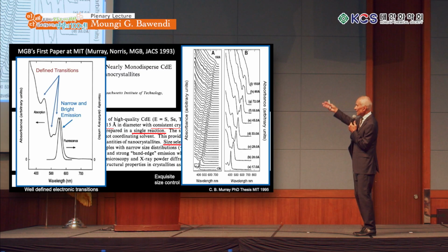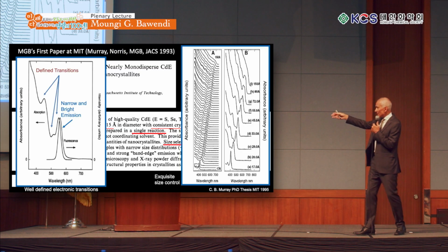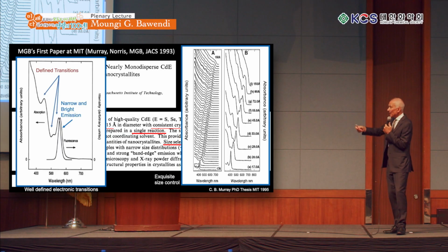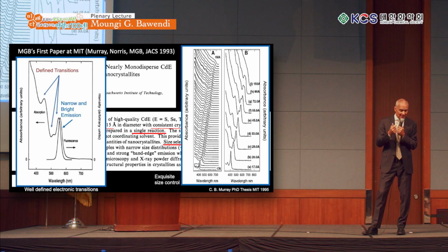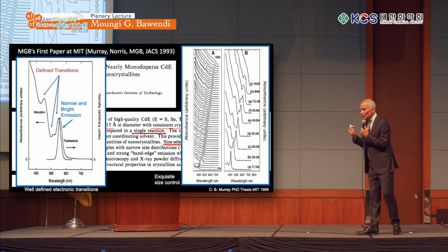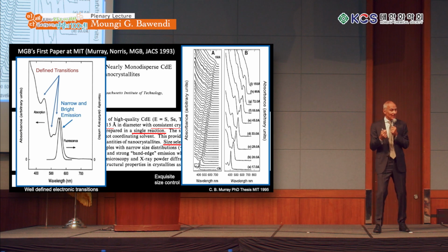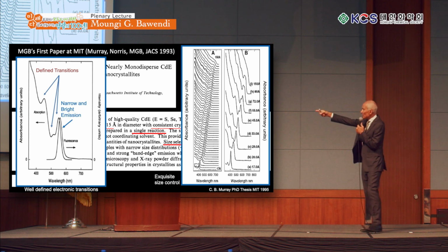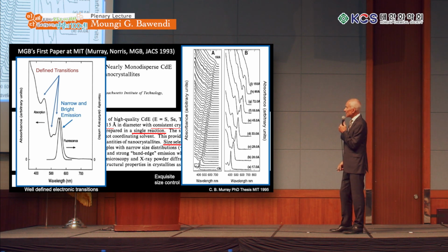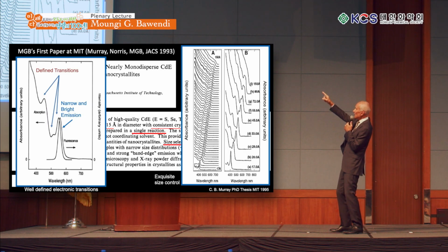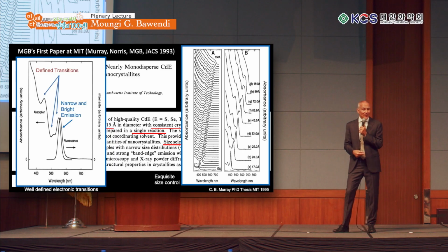The other thing that we were able to show, this is from Chris Murray's thesis, is the exquisite control that we had over the size of the particle. So on the left here, you see a series of absorptions. Going from 400 nanometers on the bottom, these are about 1 or so nanometer sized particles. And then on the very top, at 15 nanometer particles, those are basically bulk-like spectra.